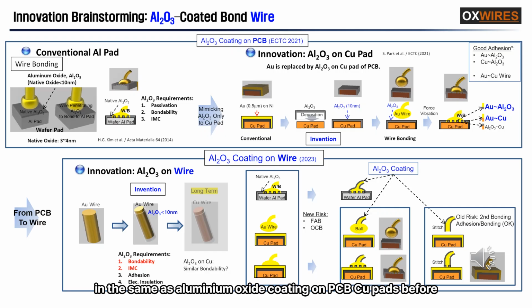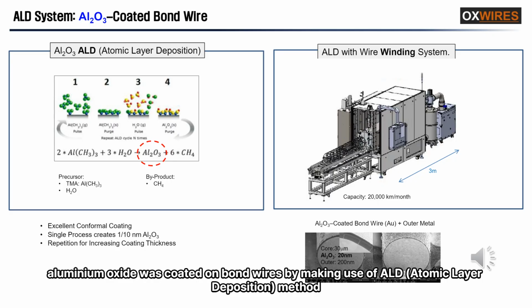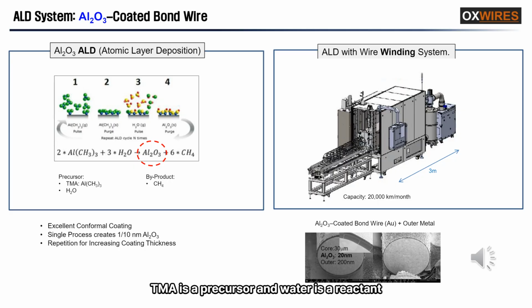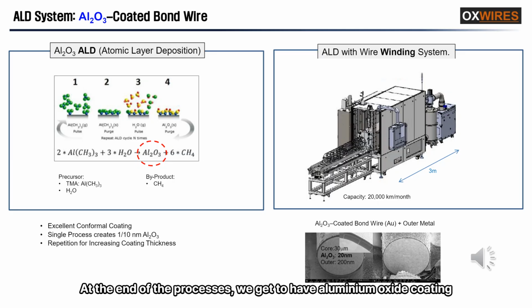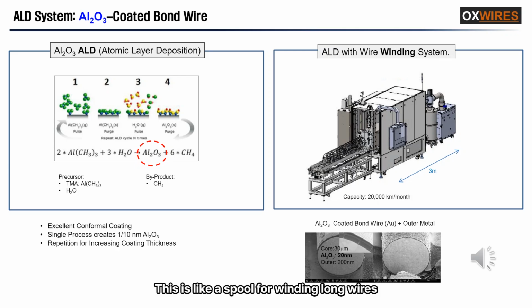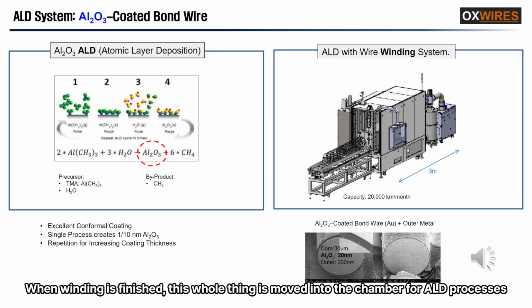pads before. Aluminium oxide was coated on bond wires by making use of the ALD, atomic layer deposition, method. TMA is a precursor and water is a reactant. At the end of the process, we get aluminium oxide coating. ALD is known for excellent conformal coating. On your right side, you are seeing a chamber for ALD coating. This is like a spool for winding long wires. When winding is finished, this whole thing is moved into the chamber for ALD processes.